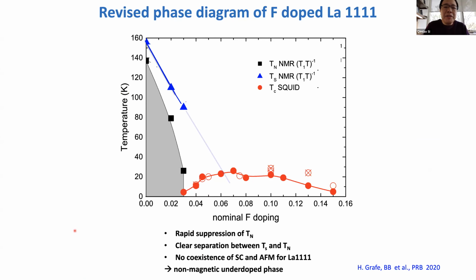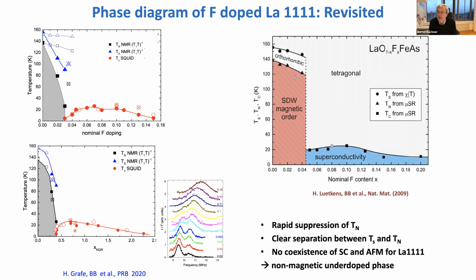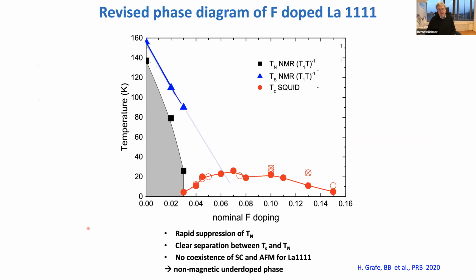Bernd, do you mind if I interrupt you for a second? No. Maybe you'll talk about it, but near the doping where the magnetic order goes to 0, say when the TN is about 20 Kelvin or so, is there something unusual about the resistivity versus temperature, for example? I cannot tell you about that. It's still, no, it looks like this close to localization behavior. Okay, thank you. I cannot tell you, in these cobalt doped compounds, which I discuss later on, this intrinsic scattering due to cobalt is so strong that I will not discuss that, but I will come back to that later. Okay, thank you. Okay. So that's the phase diagram we are dealing with for the fluorine doped compounds.